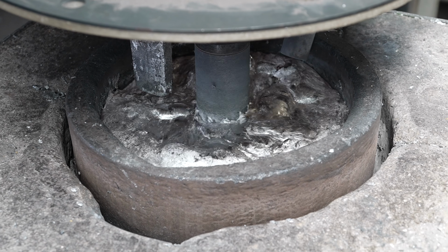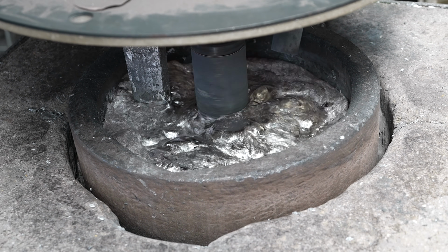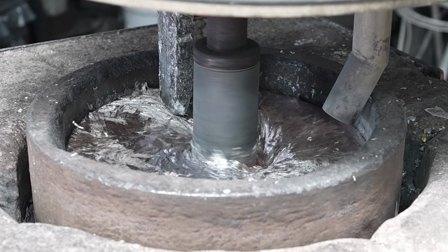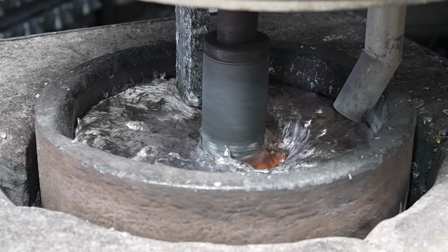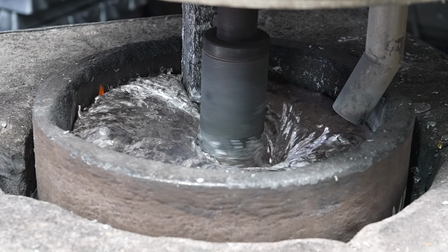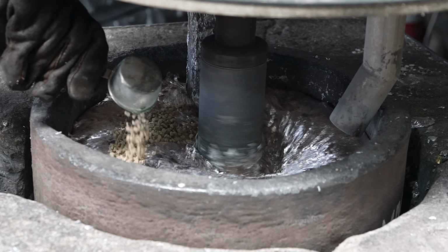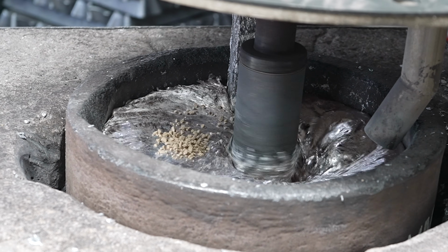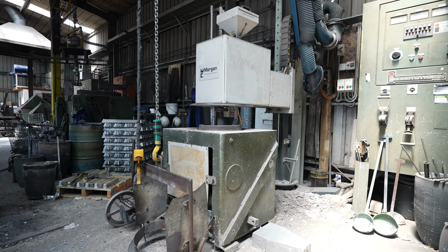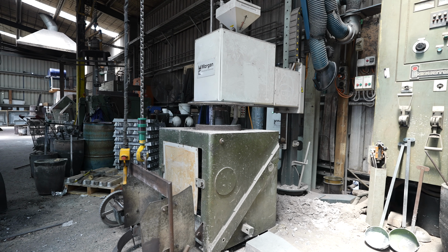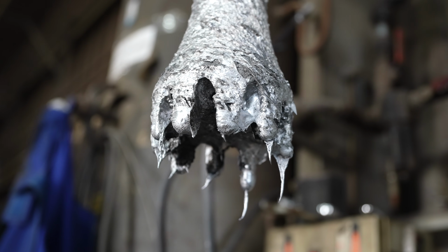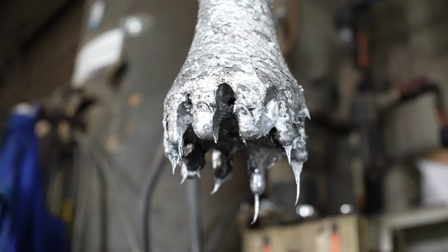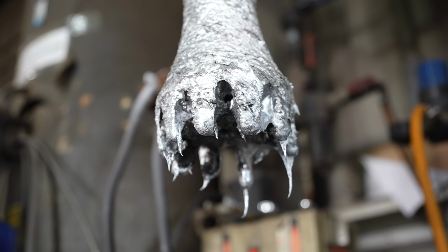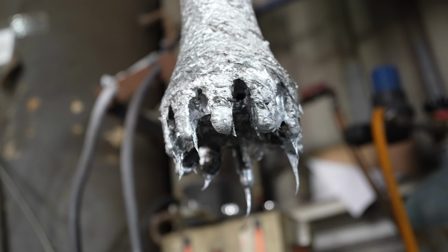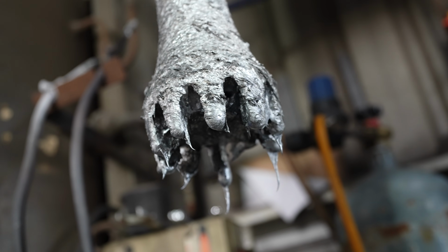And the way it works is this machine here has got a head on it, and it goes down into the bath, spins, generates a vortex, which does two jobs. It pulls the cleaning flux in and stirs it in, and then it'll slow down in RPM so that the bath sits nice and flat and the degassing process starts. So the gas that's being pumped through the rotor head is being split up into lots of small bubbles by the shape of the rotor, because there's teeth on the bottom of the rotor. And then those bubbles permeate through the melt. We do it for about 10 minutes, at 8 litres a minute, and that cleans out the oxide films